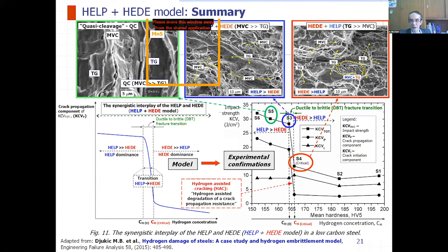So we investigated the hydrogen embrittlement mechanism. In the case of the S3 and S4 specimens, we have very similar fracture features. Here is a mix of ductile areas, predominantly microvoid coalescence due to activity of the HELP mechanism, and the initiation of transgranular quasi-cleavage fractured area due to activation of the HEDE mechanism. But you can see MVC areas are predominant.